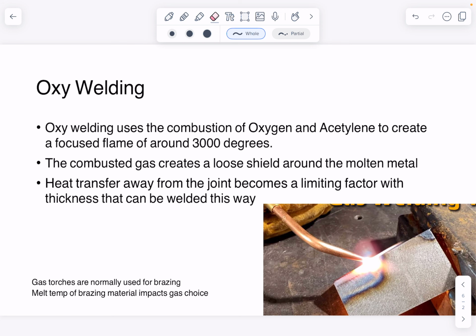The combustion gases create a bit of a loose shield. If you look at this little image here, in this area where this burnt fuel and oxyacetylene gas is, it's an oxygen deficient environment. So the steel that is molten underneath that isn't going to oxidize. If you had a look on the other side of this, you will get more oxidation and scaling because you're not protecting the underside of that joint. So it's wrong to say it isn't a shielded weld. There is a shield, it's just a very loose shield from the actual torch itself.